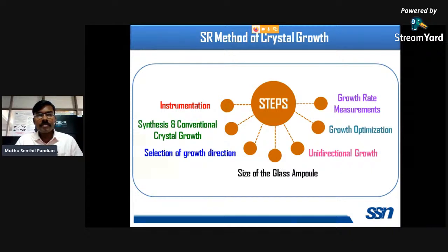So for the growth of the SR method, we have to carefully identify all the steps: instrumentation, synthesis and conventional crystal growth, and selection of different seed crystal orientations, that is A, B, C or the phase matching direction. Whatever direction, axis or plane you want, you have to select using this growth direction, and different sizes of the glass ampoule.